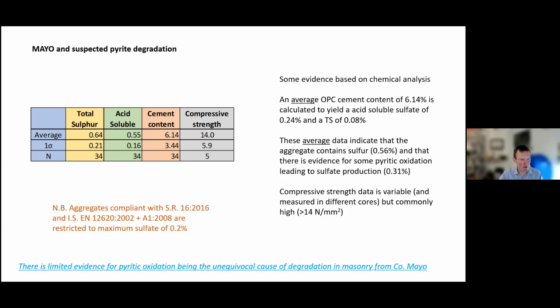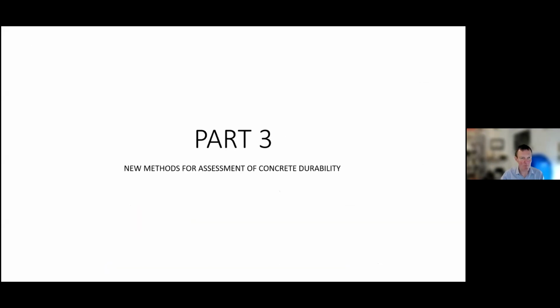The other point I would make is that the compressive strength for Mayo is quite variable, but commonly quite high. And this seems anomalous to the obvious extreme degradation that's seen in some of the houses. So this is my opinion, that there is limited evidence for pyritic oxidation being the unequivocal cause of degradation in masonry from County Mayo. So what we do know is that the concrete's wet. So that may have a big bearing. Okay, so part three, I'm going to suggest some new methods for assessment of concrete durability.